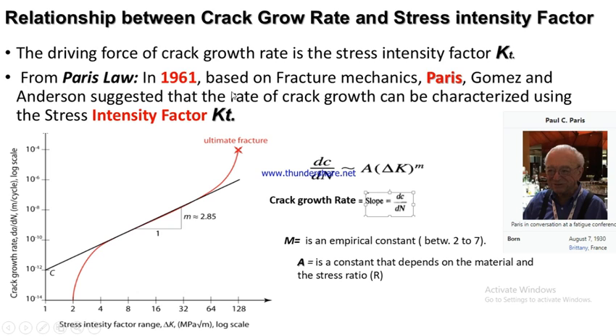From Paris law in 1961, based on fracture mechanics, they suggested that the rate of crack growth can be characterized using the stress intensity factor of the material. So like we have here, you can see these are the various stages of the previous crack growth rate profile. If we plot it against the stress intensity factor of the material, you get a particular profile that looks like this. The slope, dC/dN, is proportional to the range of stress intensity factor raised to the power of m, where m is an empirical constant between 2 and 7, which we can choose, and A is a constant that depends on the material and the stress ratio of the material we are investigating.